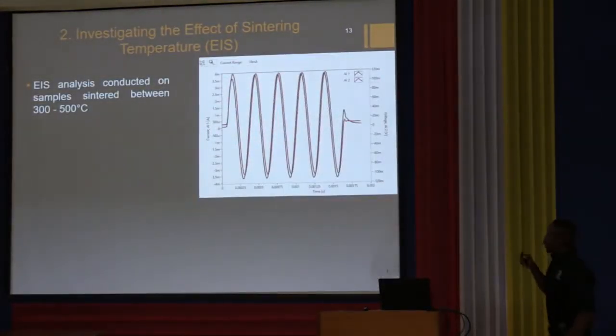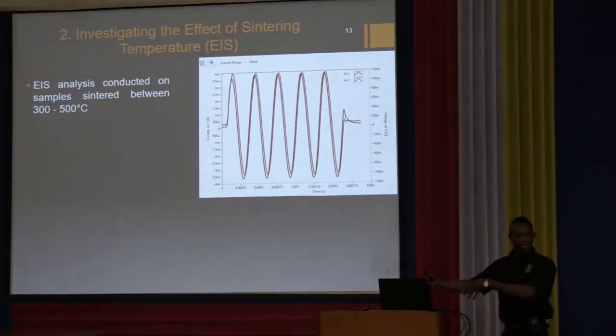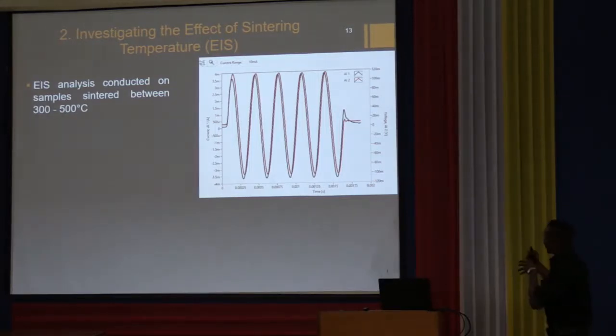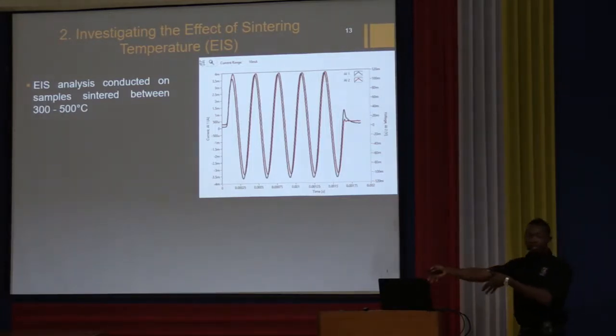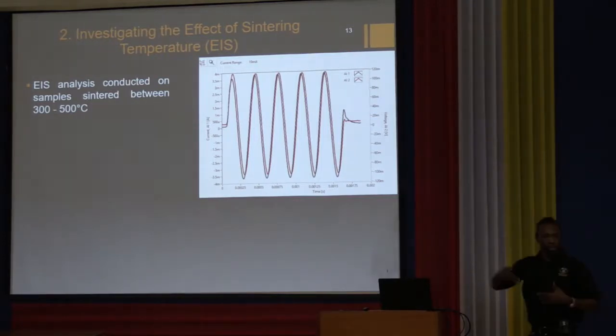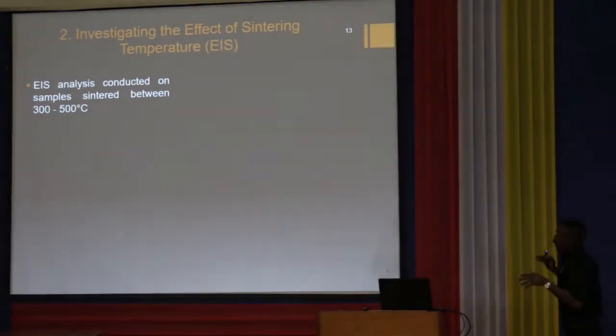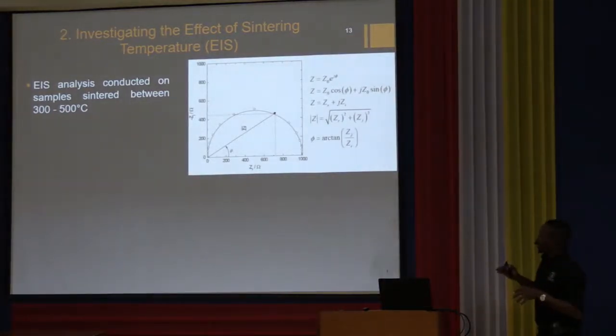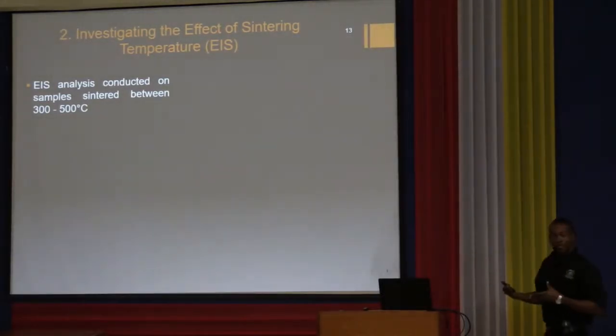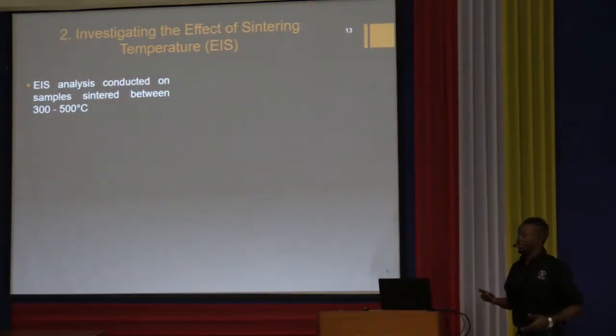Now, we carried out another analysis referred to as impedance spectroscopy. Essentially, we give the cell an AC signal, an AC current in black, and measure the current that comes out on the other side in red. And you apply one waveform, you get another waveform out. By analyzing these two waveforms, we can get a plot of the impedance in the cell, which is similar to cell resistance, and that gives us more information about how charge is transferred through the cell.